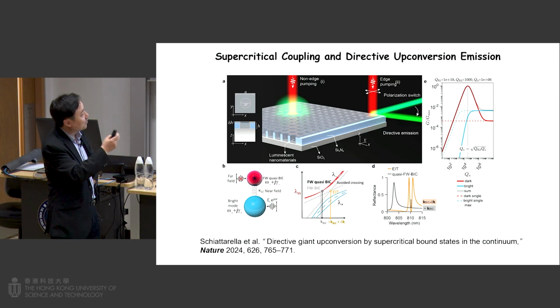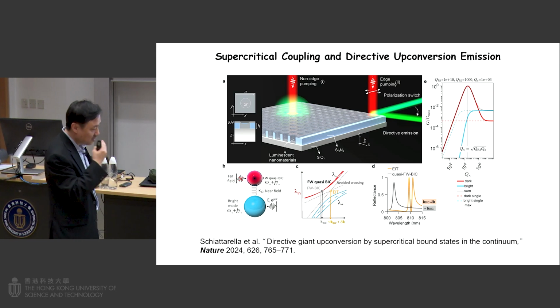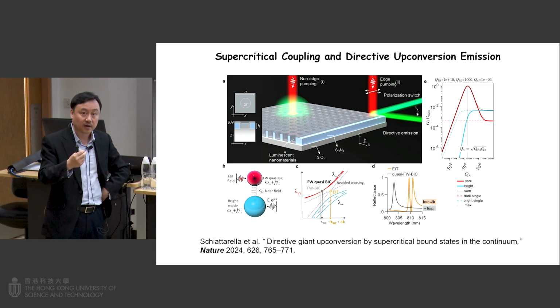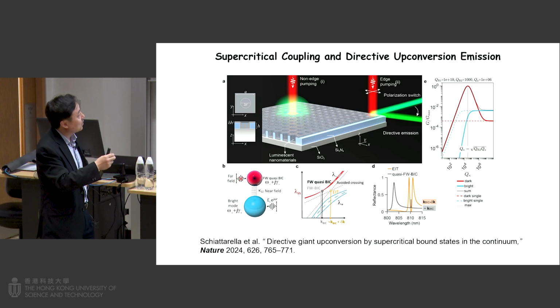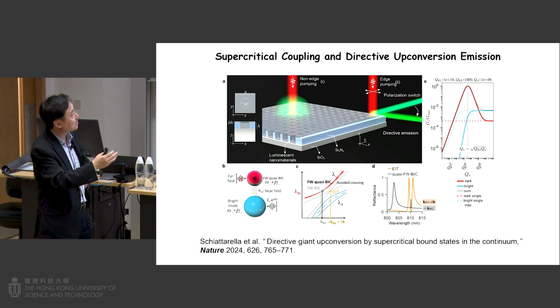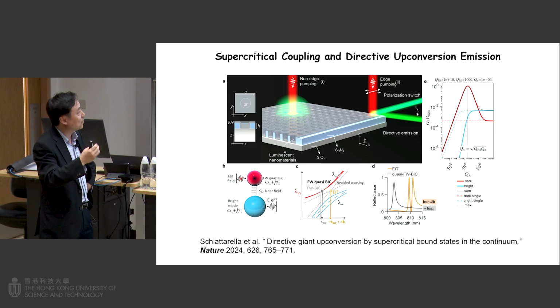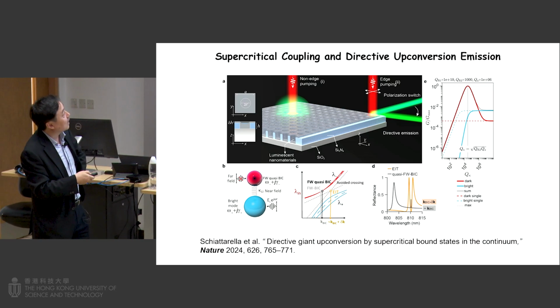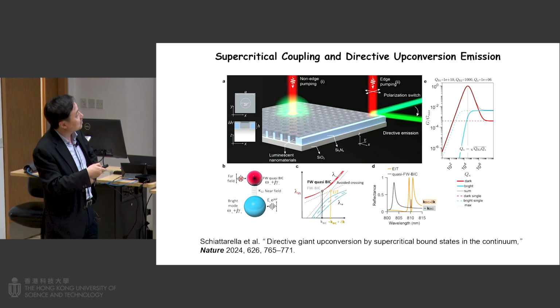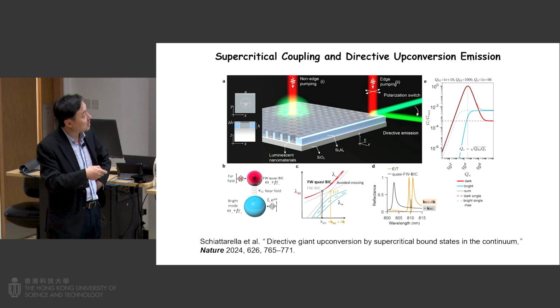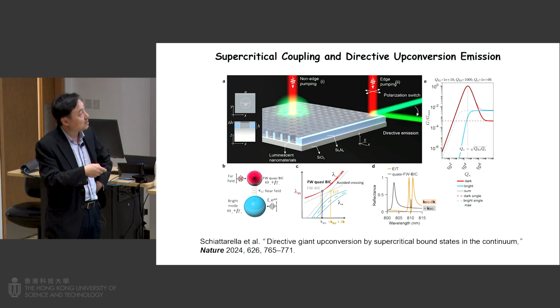Recently I've also been working with a group from Italy. My collaborator is actually a theoretical researcher, but he has the capability to fabricate metasurface materials. One of the challenges, as I mentioned, is the luminescence conversion efficiency, the emission intensity. This study showed very interesting discoveries. If you use this upconversion material embedded into dielectric metasurfaces, not only can we achieve significant upconversion enhancement, but we can also control the emission direction. You can see here, it is showing either this direction, or we can change to another direction at the edge